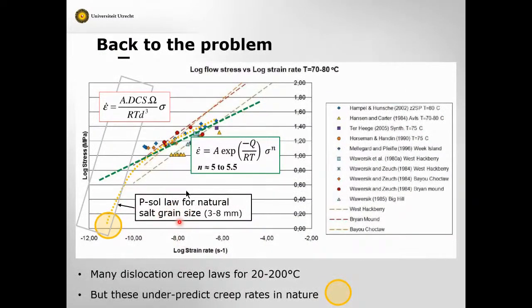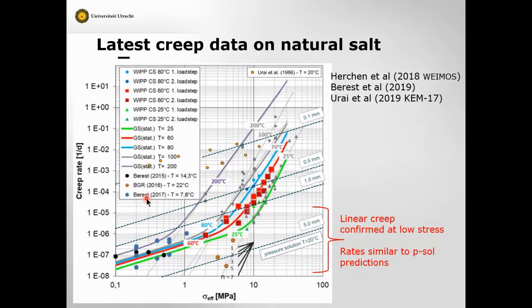So coming back to the problem then, here's our dislocation creep behavior, which we have a good microphysical basis and lots and lots of data and constitutive laws, and our pressure solution law that I just described, how we got that for fine-grained salt. If we extrapolate that grain size to natural salt grain sizes of a few millimeters, it falls down here. It's in this band, right? We're looking at slopes in this band. You see, then it does actually offer an explanation for the relatively rapid creep one sees in natural salt compared with what you'd expect extrapolating dislocation creep. I have always felt this is quite convincing that it really is very likely to be this transition at low stresses.